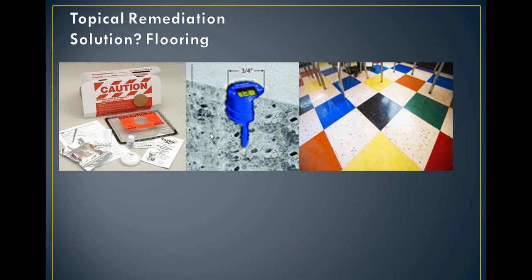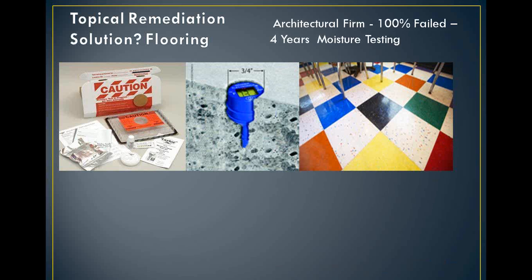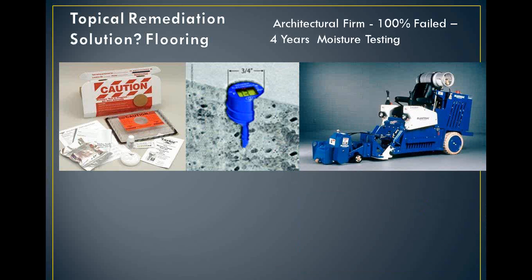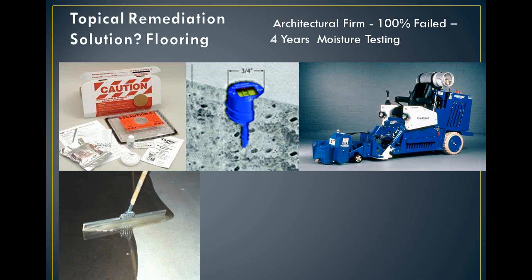However, in the case of approximately 60% of the commercial projects, an extra step is necessary. An architectural firm in Boston told me that 100% of their projects failed these two tests, so they simply built this into their process. And this process is designed to deal with all that extra water in the concrete. So they take one of these machines and run it around the floor as a shot blaster, shooting lead BBs into the floor, ripping off the top matrix so that this material can be applied. This is an epoxy moisture remediation material that slows down the rate at which moisture leaves the concrete slabs. Doesn't stop, but it slows it down.